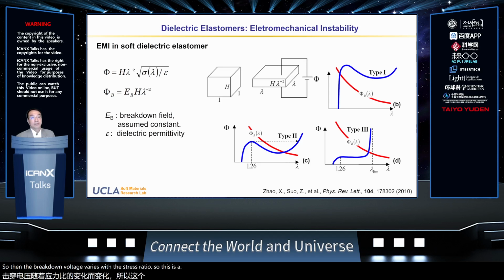So with a stiff material, the type 1, the maximum strain you get is relatively small. Okay, if the rubbery polymer is soft, the strain or stretch ratio lambda increases with the voltage applied, but when the voltage reaches a certain level, you will see an equivalent stretch ratio point, a snap-through. Which means that the maximum stable strain you can obtain from this kind of type 2 soft dielectric elastomer is only lambda equals 1.26.